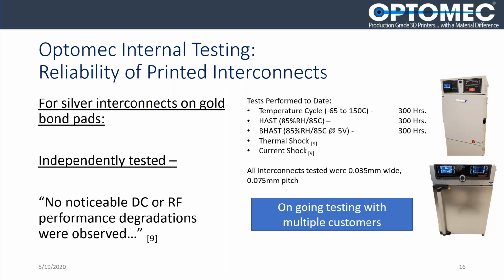Just another note on the reliability of the printed interconnect. We've spent quite a lot of time with a large number of companies to understand the requirements associated with what these devices are subjected to, both for military applications or semiconductor, be that JEDEC or otherwise, and have the capability to do these tests internally here at Optomec. So we have some humidity testing chambers and some temperature cycling and current and thermal shock capability that we have subjected our silver interconnects on gold bond pads in this particular case to. And we're not just doing it internally, other people are also doing this reliability testing.